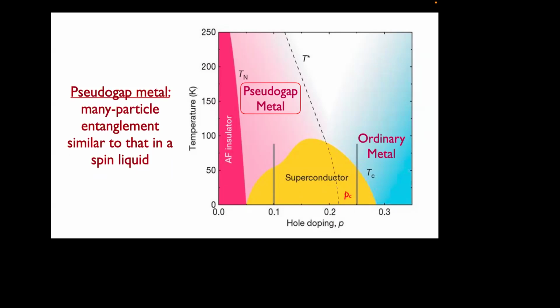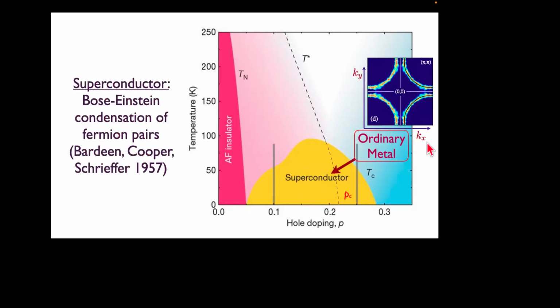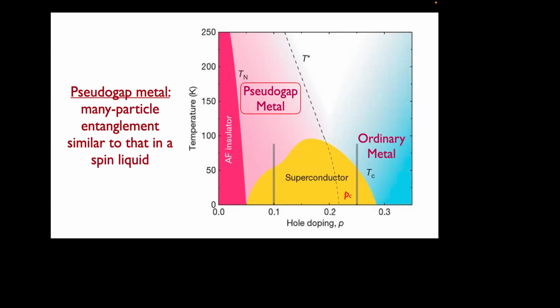Okay, but what about as you move to the left where the Tc is really highest? Now, if this kind of picture held through the entire phase diagram, well, then I wouldn't be standing here. The problem would have been solved. But that's not what happens. So what you find quite remarkably is that the metals you see above Tc at lower doping are nothing like Sommerfeld's metal. Most dramatically, that happens in what's called the pseudogap. I'm going to say a bit more about this as I go along. And the modern understanding is that you really need a drastic modification of Sommerfeld's theory, as formalized by Landau a bit later.